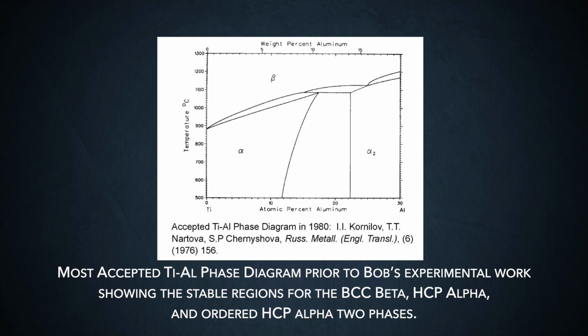And debatable in addition to whether there would certainly be a two-phase field between each of these two single-phase fields of alpha and alpha 2, but whether that two-phase alpha plus alpha 2 phase field actually went up to high enough temperature that it intersected the body-centered cubic structure. And most of the diagrams which people were concluding to work with showed this intersection. And so that was the part of what I set out to clarify.